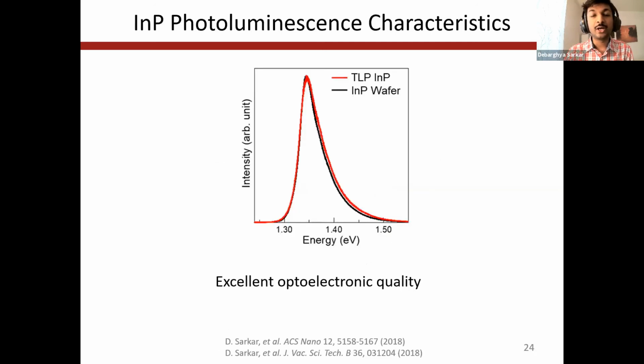Speaking of photoluminescence, this plot shows a typical photoluminescence of the indium phosphide grown by the TLP method, given by the red curve, and is compared with that of a commercially available single crystal indium phosphide wafer, given by the black curve. As can be seen, the peak position and full width half maxima of these two curves are pretty similar, indicating that the TLP grown materials have optoelectronic quality similar to that of gold standard commercially available single crystal wafers.